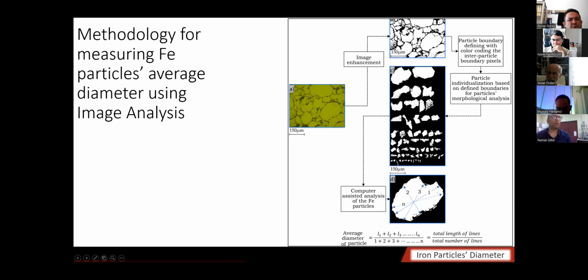It can also give you the roundness of the material. What it will do is measure the diameters of all particles, and it will see which one is different from which one and by how many micrometers. And then it will give you a measurement of the roundness. A circular particle is going to be reported with zero deviation from the diameter, and it will be called a perfectly round particle.